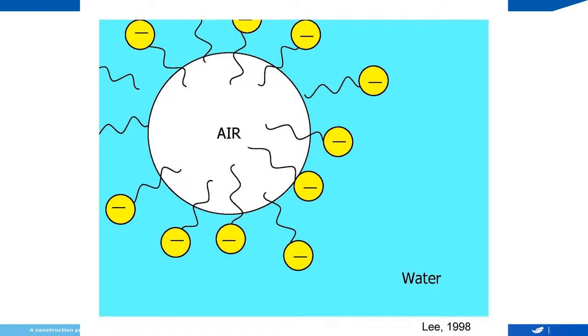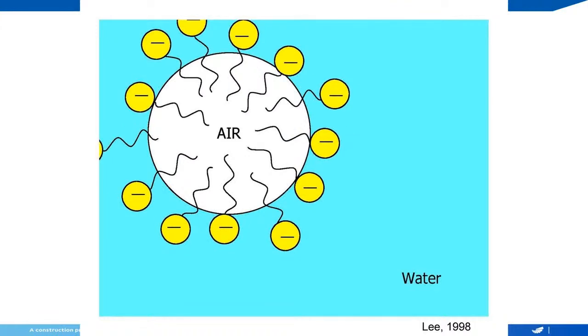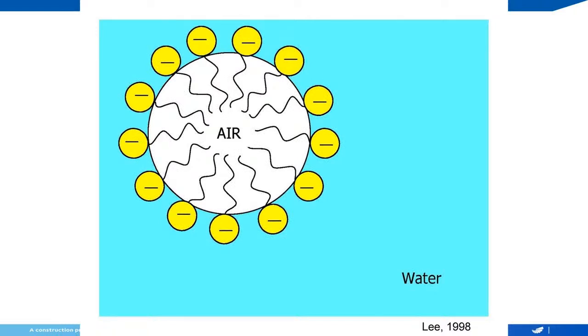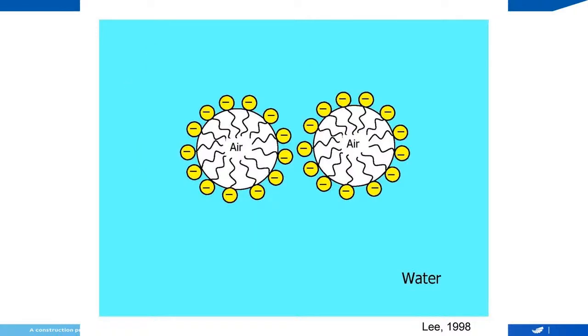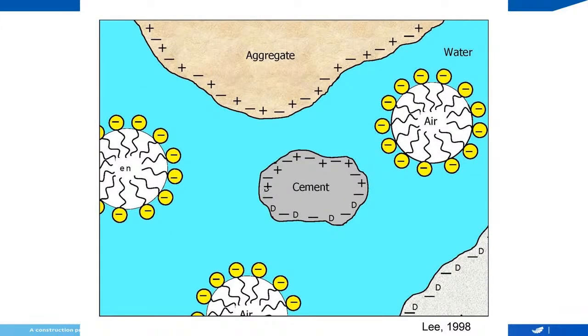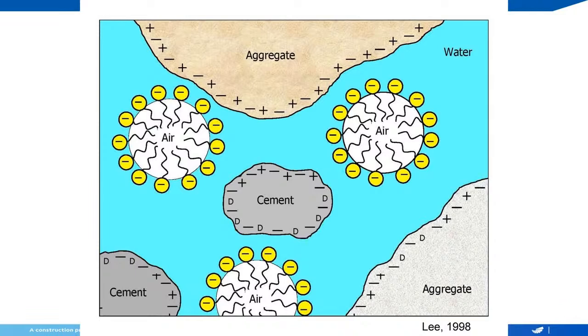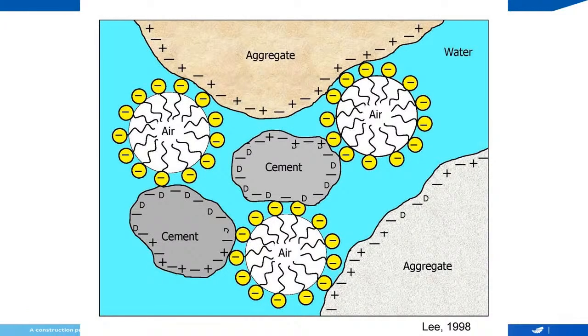So when you mix concrete, you're always generating some air. That air is mostly going to go away as soon as you stop mixing. When you put the air entrainment in there, it stabilizes those bubbles that are created during mixing, and they don't go away. Now, some of them will obviously dissipate over time. The bigger bubbles will tend to come out quickly, and we're going to talk about that a little more later. So then you'll see, again, we're getting more of these molecules around this bubble. We're getting more bubbles. I'm going to go through this fairly quickly. And then you'll see that you'll get the aggregate. You have the cement.